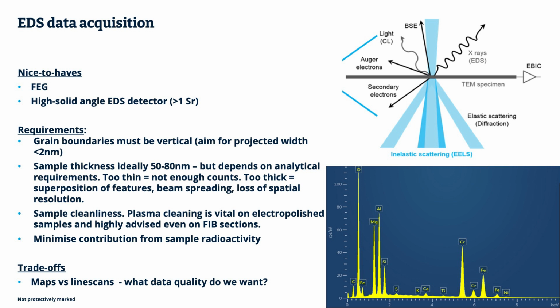And high solid angle, high collection efficiency of those X-rays is obviously vital. Modern high-end analytical detectors for TEMs tend to be about 1 steradian in collection angle. I think the most that is currently offered is an FEI machine, which is claiming to offer 4 steradians of detection, which is crazy. I mean, that's most of the sky covered with a detector, and is an enormous step up from where things were. When I first started using EDS, a big detector was about 0.15 steradians. So we're collecting a lot more data. We can do a lot more with it these days.